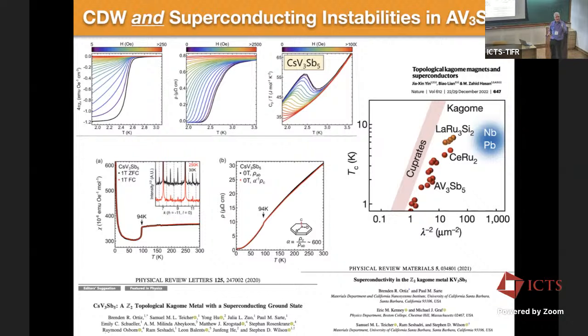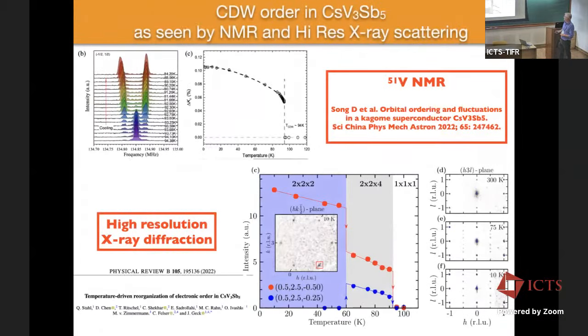And actually, some of the physical parameters associated with this material vary a lot, or a fair bit, from sample to sample and this sort of thing. This one doesn't, right? This 94-degree anomaly is there in pretty much every sample, and it's bang on at 94 Kelvin. And that'll be important for reasons that I'll go into in just a moment.